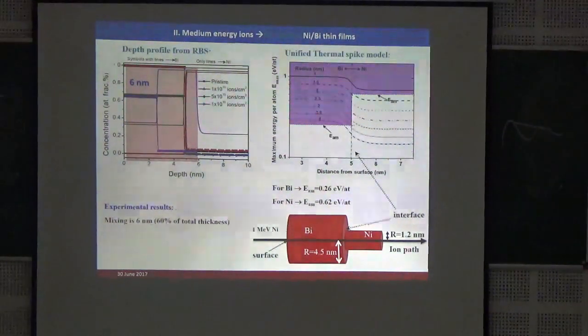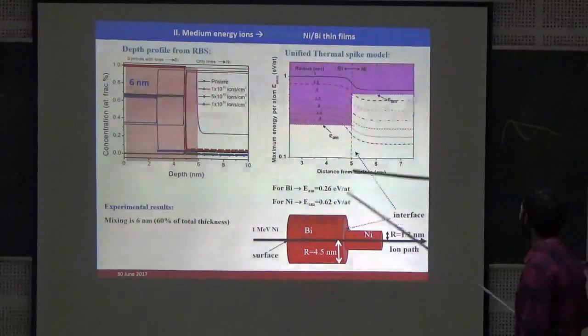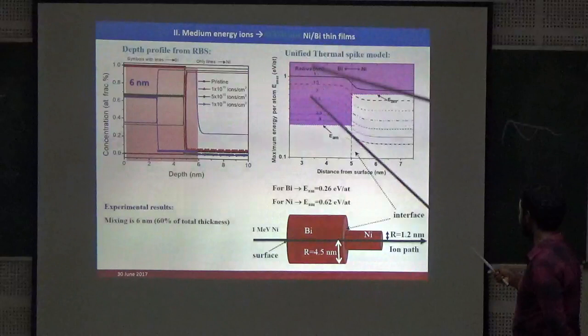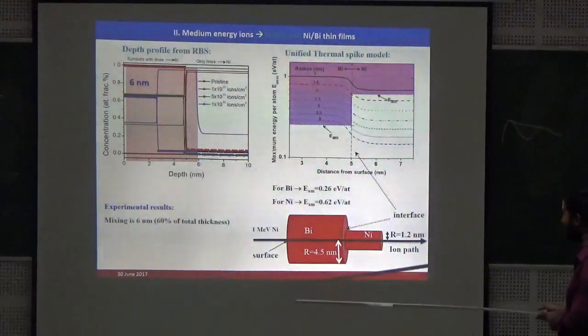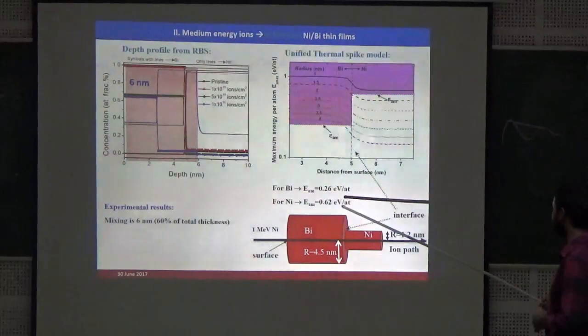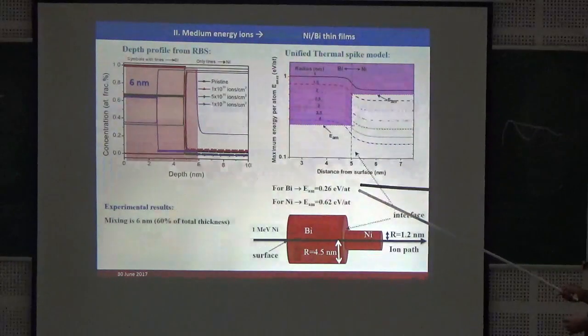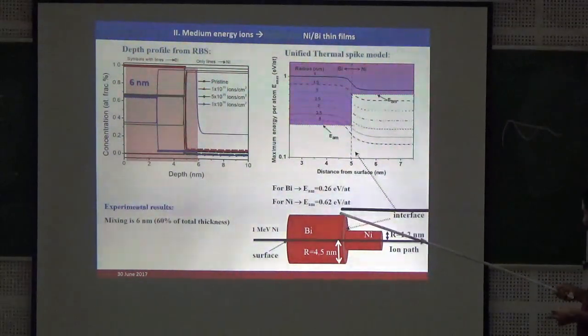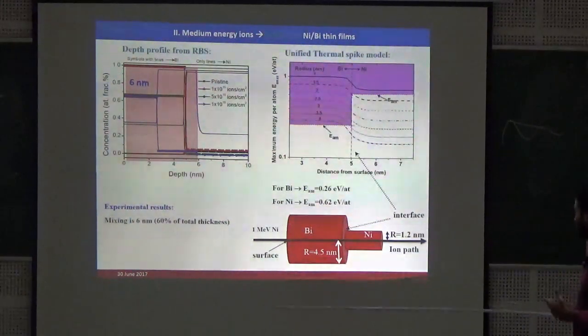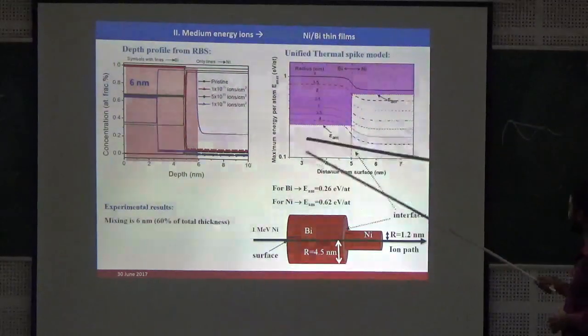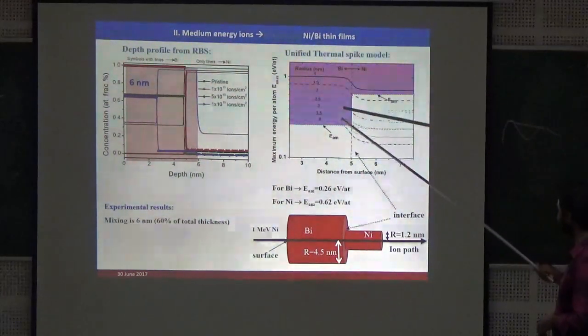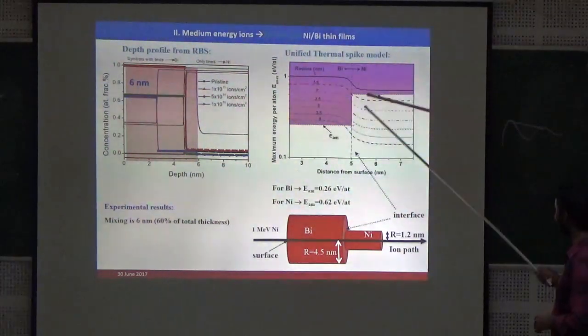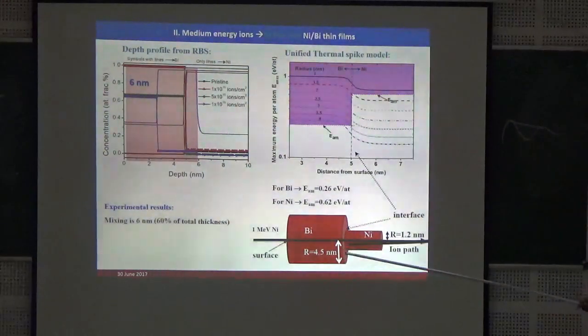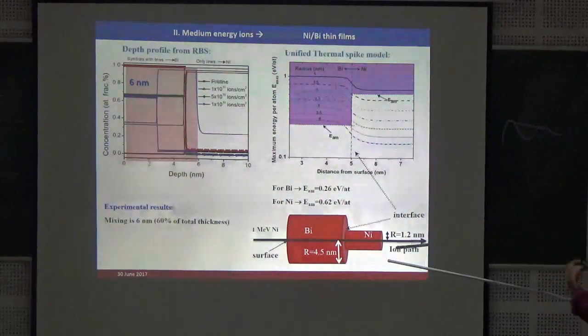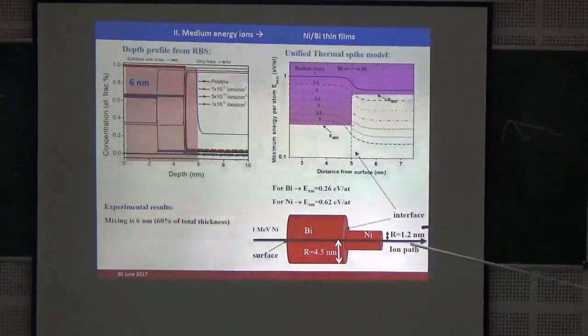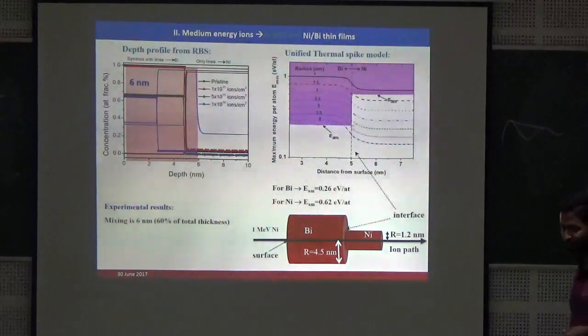So we have performed unified thermal spike model calculations in these cases. Here you can see we have plotted the maximum energy per atom as a function of distance from the surface. In order to drive bismuth and nickel to molten phase, we have to supply 0.26 electron volt for bismuth, and for nickel it is 0.62 electron volt. So if you supply that much energy, we can drive these layers to the molten phase. I have highlighted this pink region, which is more than these values for bismuth and nickel. So here you can see almost 4.5 nanometers of molten phase in case of bismuth, and 1.2 nanometer of molten phase in case of nickel. So this must be the reason for enhancement in the mixing.